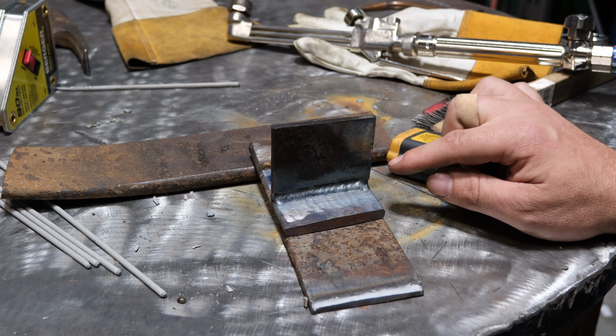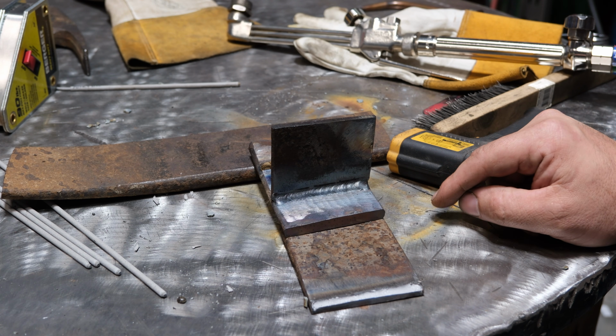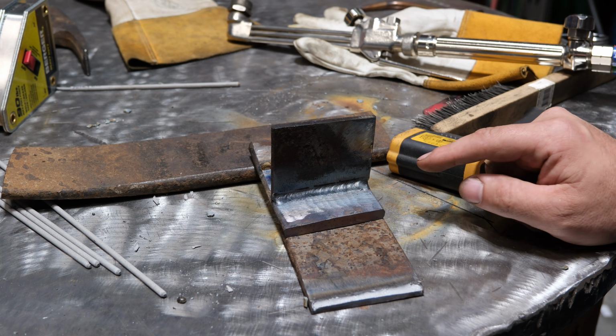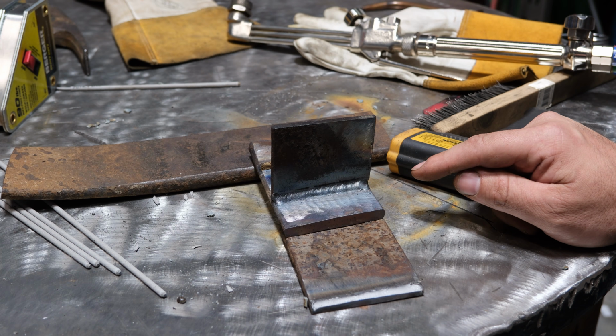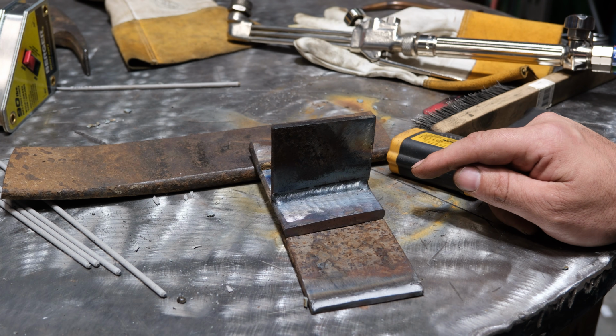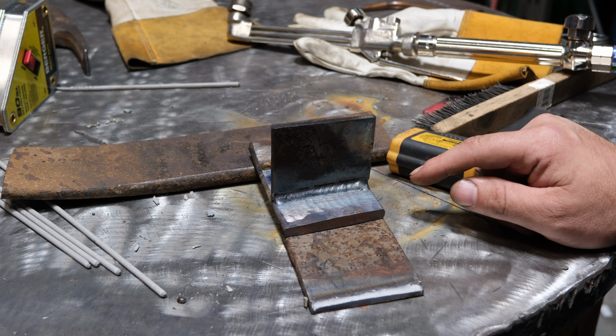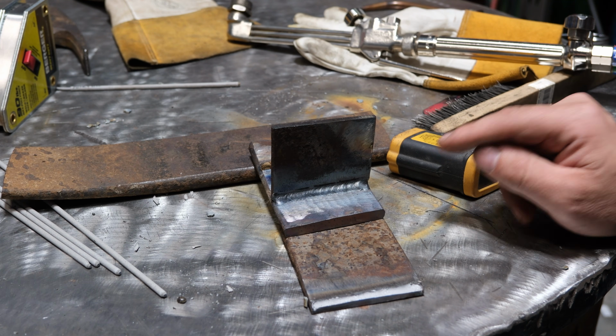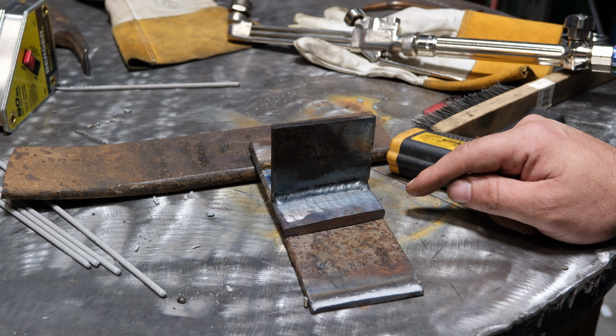However, I would not weld this junk with 100% CO2. That will typically make a much harder weld on this material, and it'll be far more prone to failure, even in the sake of a simple repair just to get you from point A to point B, and that's it. So do not use 100% CO2 on this.